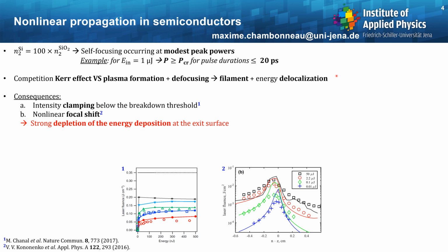Two consequences of this. First, there is a saturation of the intensity below the breakdown threshold of the material, as you can see here. In other words, increasing the input pulse energy will not lead to an increase in the laser fluence. Second, there is a nonlinear focal shift. As you can see here, the more the energy, the more the focus is shifted upstream the laser. And taken together, those two consequences lead to a strong depletion of the energy deposition at the interface.